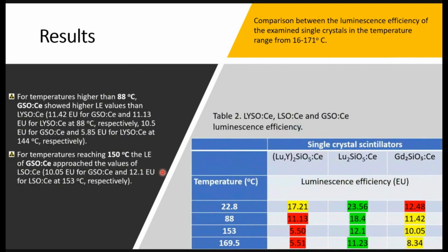And finally, we can see the luminescence efficiency results in table 2. In the lower temperature range, the pure lutetium crystal dominates. It is followed by the lutetium-yttrium crystal, and the lower values appear for the gadolinium crystal. However, in higher temperatures, we can see that the gadolinium crystal shows higher luminescence efficiency values than the lutetium-yttrium. And at even higher, we can see that it even approaches the pure lutetium crystal, which is the most expensive of the three crystals that we examined.